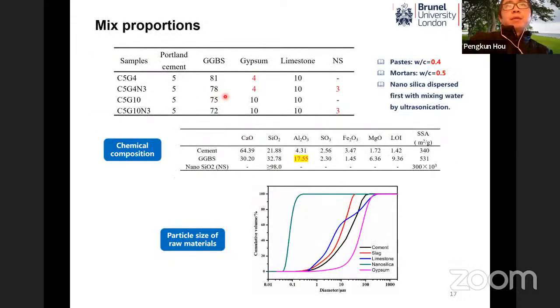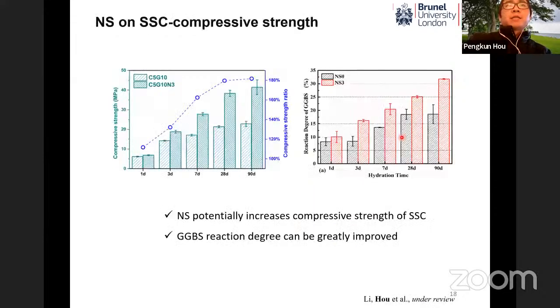So to do that, we made the proportions with two dosages of gypsum, 4 and 10%, and we added 3% of nanosilica, and the GGBS we used has an aluminate content of about 17%, and then we did the hydration and the mechanical testing. So let's first see the compressive strength. With the addition of nanosilica, for example 3%, we can see that it can increase the compressive strength of SSC. For example, at 28 and 90 days, the compressive strength can almost double. And then when we analyze the hydration degree of GGBS, it can be found that the hydration of GGBS can be increased by nanosilica.